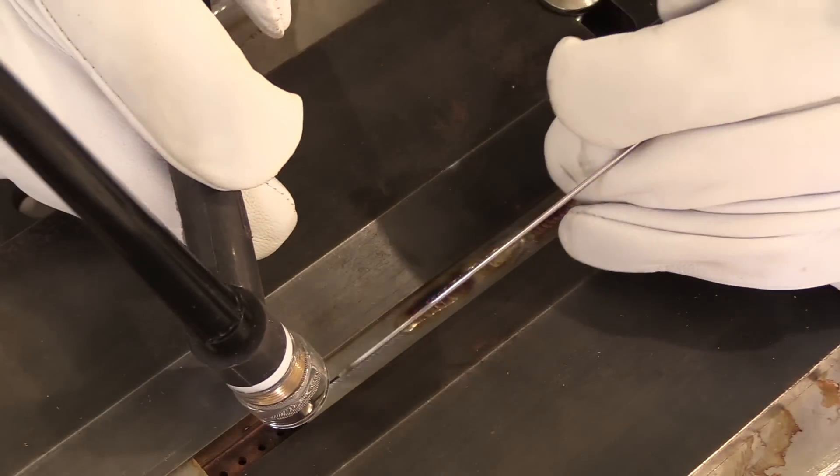But I don't want to back off the amperage right away. I want to blend in. I want to overlap that thing, add a little bit less filler as I take two or three dabs, and then start to taper that amperage while I keep moving the torch to create kind of a comet trail or teardrop effect.